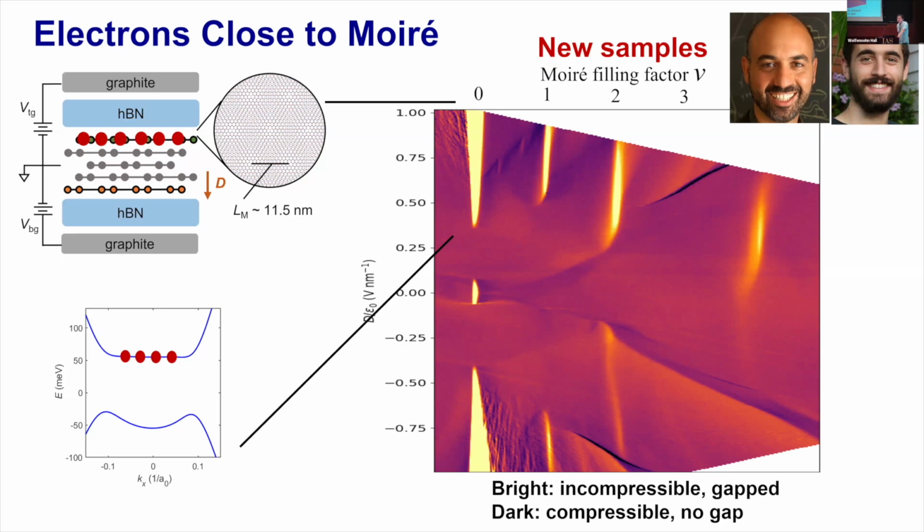I have a question about how you make the samples. Do you intentionally grow them rhombohedral, or like naturally rhombohedral parts, you make your devices there? Yeah, so basically you randomly exfoliate and you use this infrared microscopy to look for the region that's rhombohedral. And you have to cut it out from the rest of the flake in case the domain wall moves and kills the rhombohedral. And then you try to pick up the rhombohedral flake with hBN and put it down. But starting from a rhombohedral flake doesn't mean you'll get a rhombohedral eventually, because hBN is super smooth and the rhombohedral is not the most stable stacking order. Most of the time, rhombohedral become Bernal.